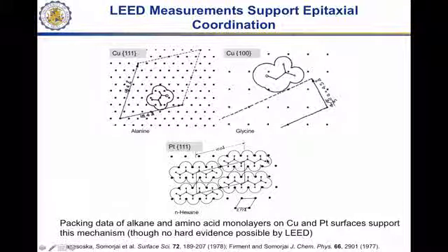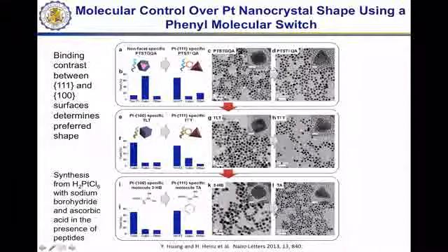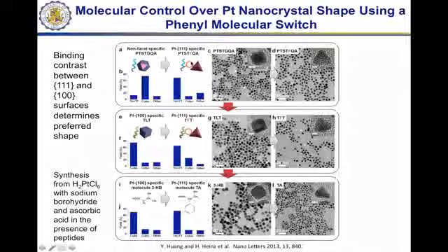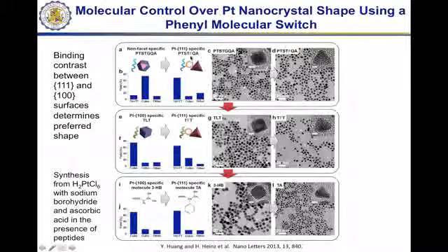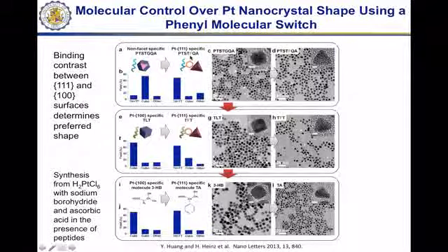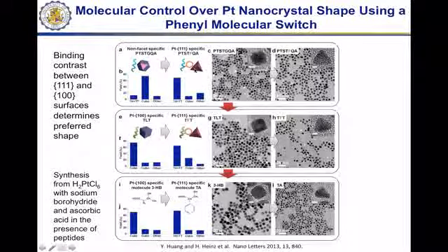So yeah, then those methods here, we have also applied them to make some specific materials predictions. For example, by computation of binding energies and so forth, we were able to say that if we have phenylalanine containing peptides versus some other less facet-specific peptides, the attraction to 111 facets increases a lot.